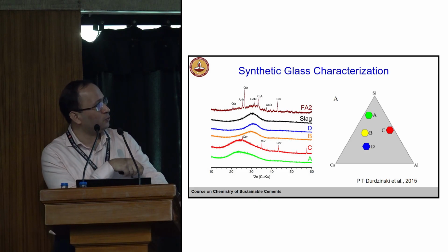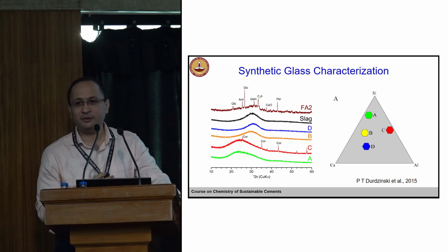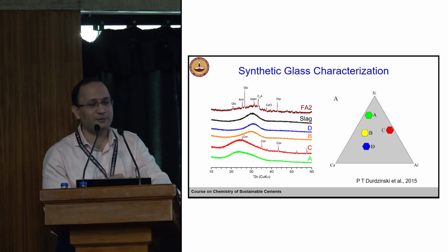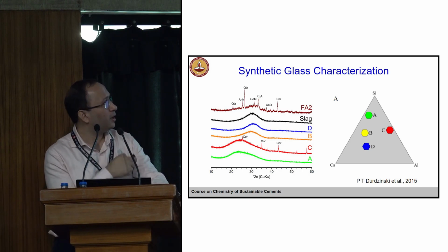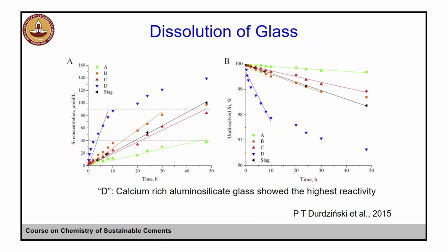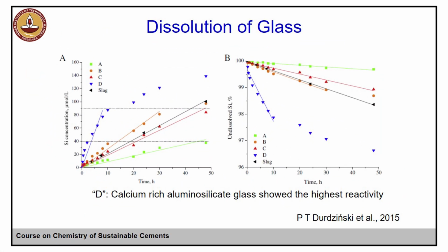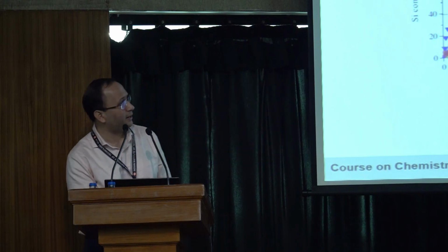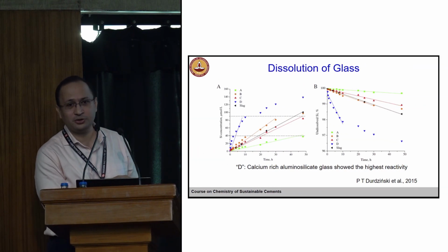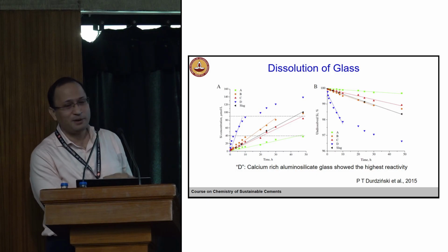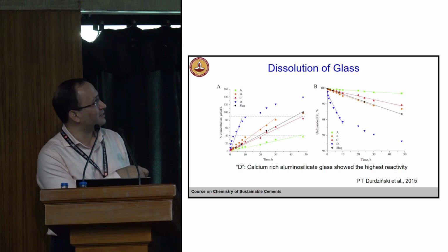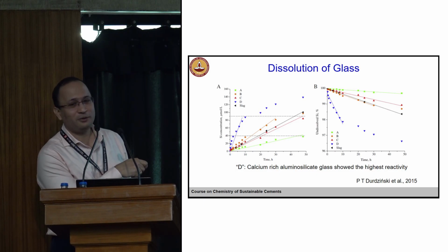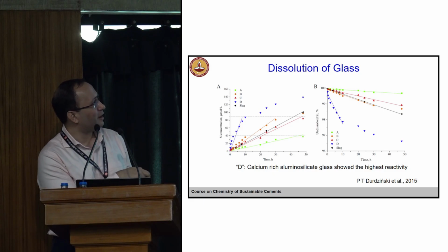And if you want to show it on this ternary phase diagram, you can see where it would be. We are interested in whether all these different types of glasses react similarly or there is a difference. We would like to know the difference in reactivity. So what they did, they dissolved the glass. Reactivity, simple: we want to look at how fast glass is dissolving. So we can track the silicon concentration with time. If we plot it, we see some differences. We see the blue one, which is D, a calcium-rich aluminosilicate, is here compared to other glasses.